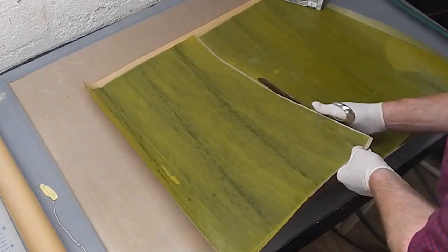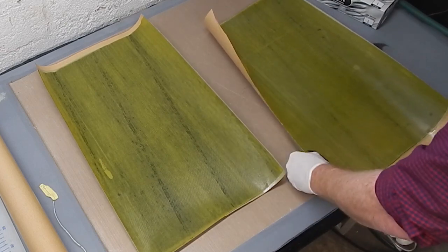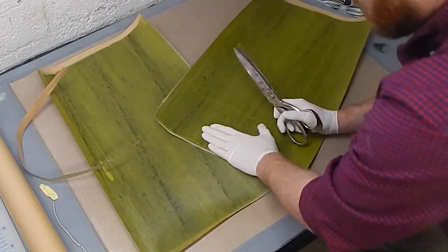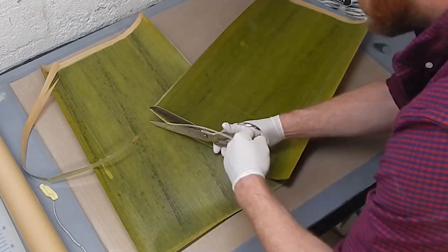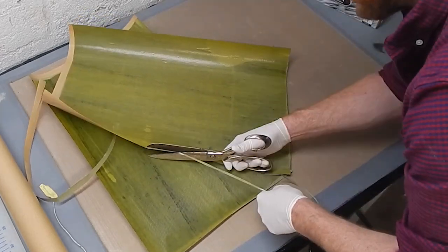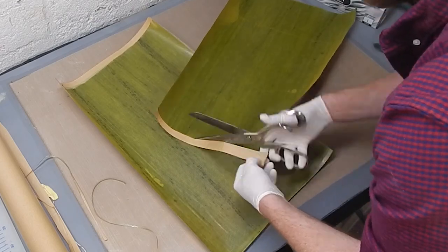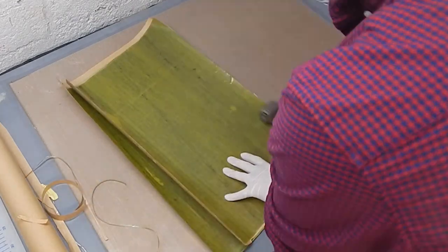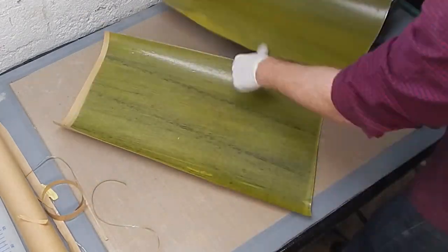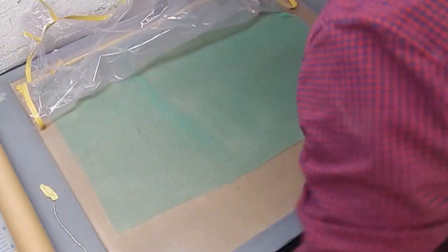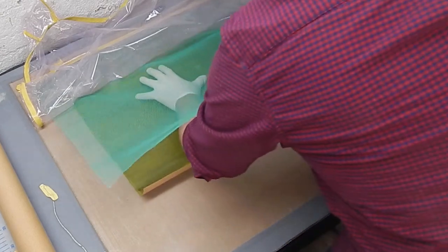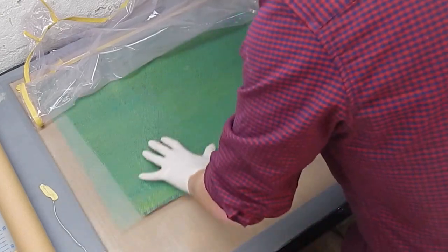And then I'll give it a quick debulk, which is ideally done warm. I've got a warm table here. It's probably 100 degrees Fahrenheit, just warm to the touch, enough to make the viscosity of the glue film a little runnier, so lets the air out, and I've got to do one at a time because I don't have enough room out of the bag.